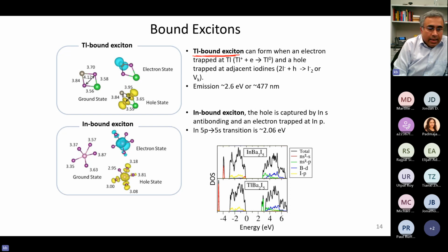What we found is that the thallium can trap an electron like so, at the thallium P state, and a hole can be trapped at an adjacent iodine, in not just one iodine. It's like a VK center. VK center means two iodine atoms come close to create a VK center. That is the hole trapping. You see that normally two iodine atoms are separated by 4.12 angstrom. But then when a hole is trapped, those two iodine atoms capture the hole, and they shorten their bond length like so, from 4.12 to 3.59 or so.